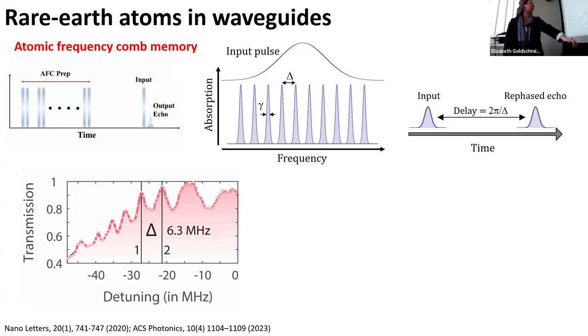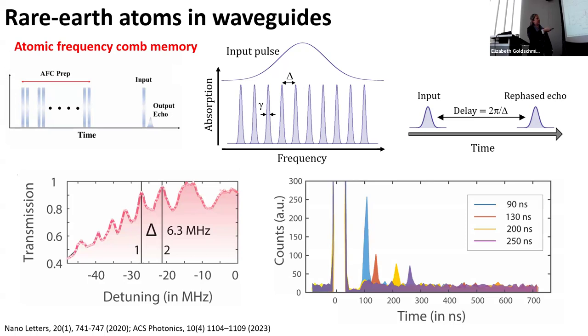So the finesse of the comb, which is the ratio of the width to the spacing or the spacing to the width. This is a comb of finesse, like, I think not quite two, which is okay. This is not real, that's an artifact of how we do our measurement. But so we can make a comb with some spacing, right? And then we can do our protocol, and then we can vary the spacing of the comb and look at the echo that comes out. And so we can build a comb to store for 90 nanoseconds, 130, 200, 250 nanoseconds.